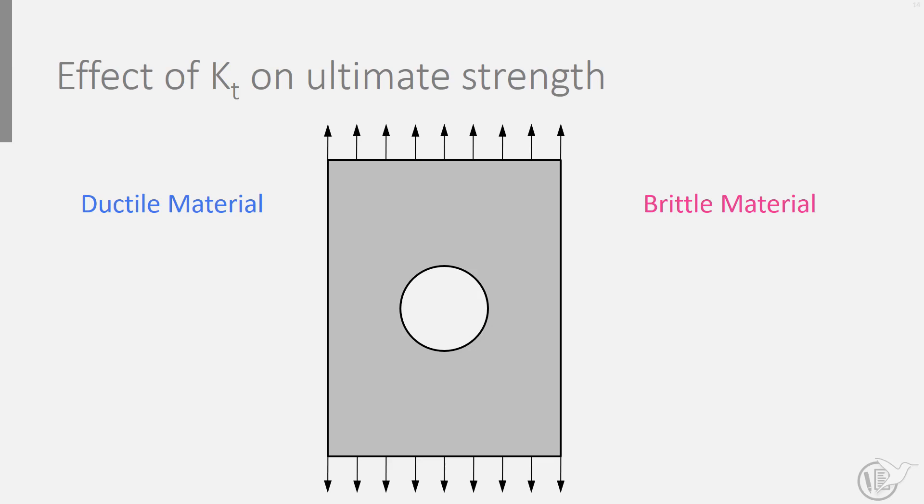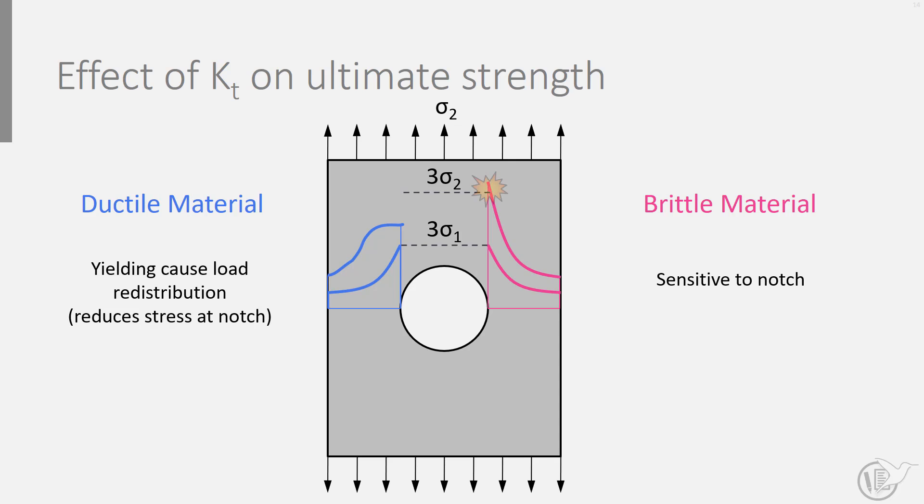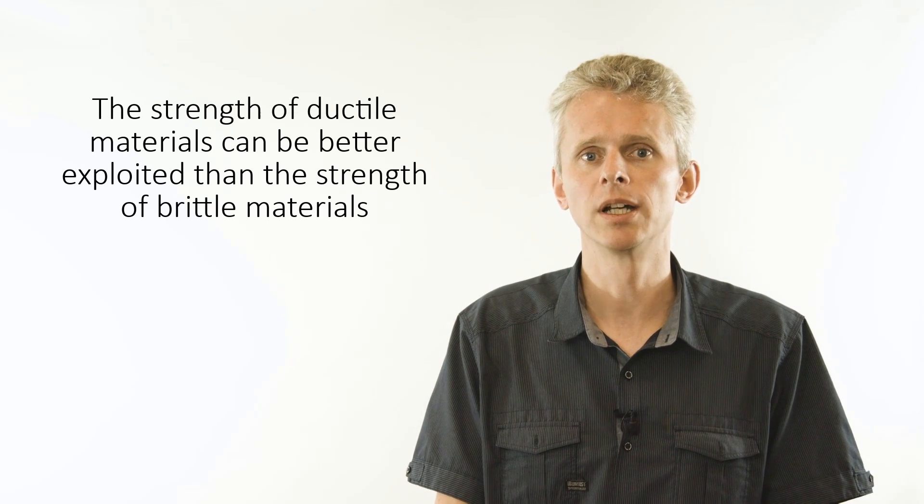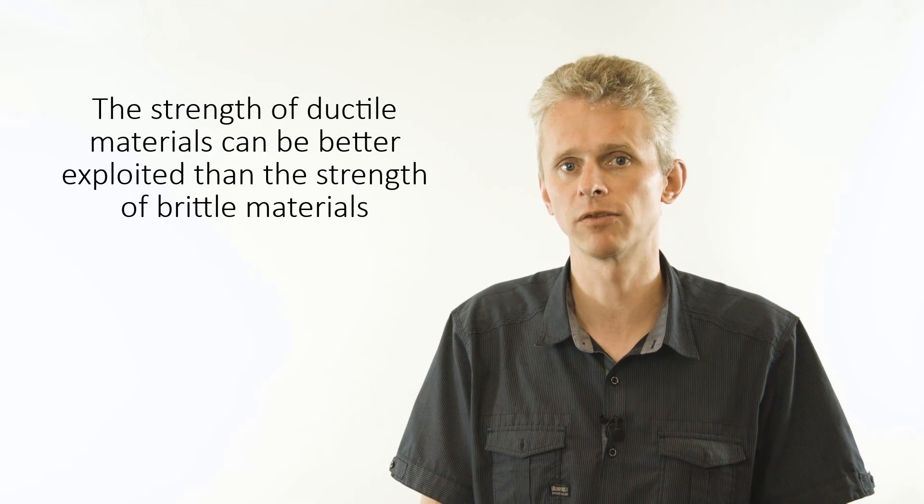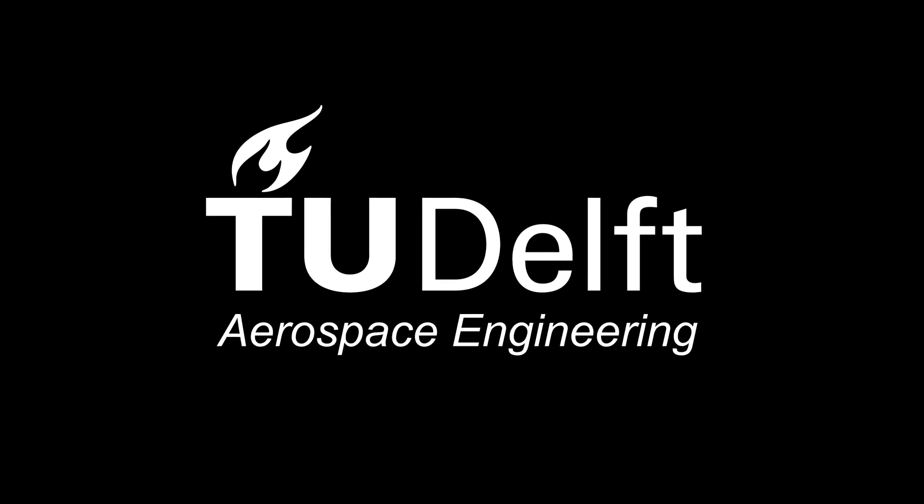The stress concentration factor is a linear elastic concept. Depending on the ductility of a material, peak stresses may be limited by plasticity compared to what is calculated assuming linear elasticity. This ductility is favorable in case of notches. As a result, ductile materials are less sensitive to notches compared to more brittle materials. Effectively, this means that strong and brittle materials cannot be loaded as much as weaker and more ductile materials. Or to rephrase it differently, the strength of a ductile material can be better exploited than the strength of a brittle material.